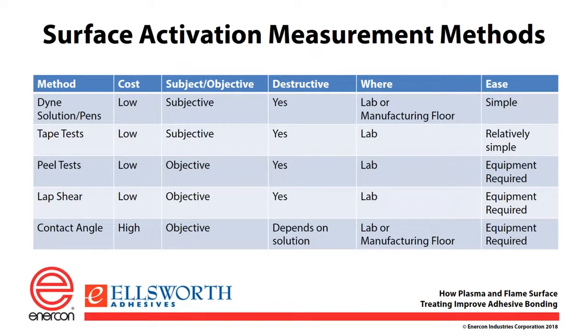Those are good indicators of adhesion. They are not perfect indicators of adhesion. There are a number of materials out there that actually, with a higher contact angle, I should say, or a lower Dyne, actually bond better. So again, this is a good method, but what this does is help us understand what we're doing to the surface. I personally prefer contact angle.